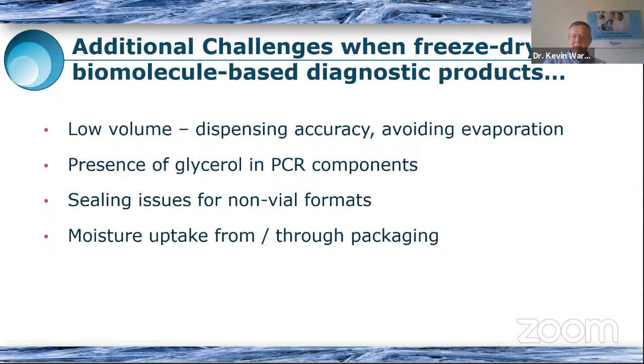And just to look at some of the additional issues with diagnostics. So some of the issues with diagnostics is that they often are lower volume compared with vaccines. So with vaccines, usually between 500 microliters and several milliliters. Well, with some of the diagnostics, there might be tens of microliters. And so dispensing accuracy, avoiding evaporation before you've started freeze drying can be an issue. Some of the components can be supplied in the presence of glycerol-rich solutions. There can be sealing issues if they're not in vials, and there can be moisture uptake from or through packaging.